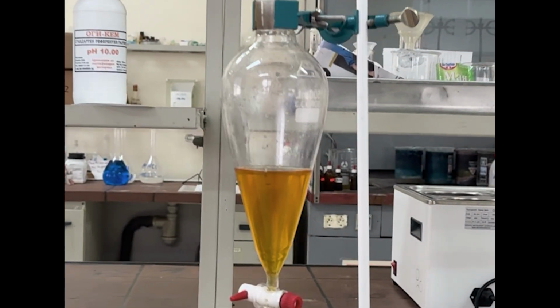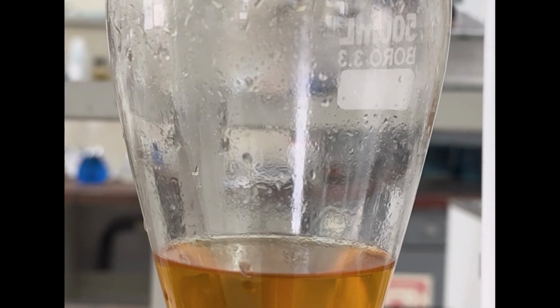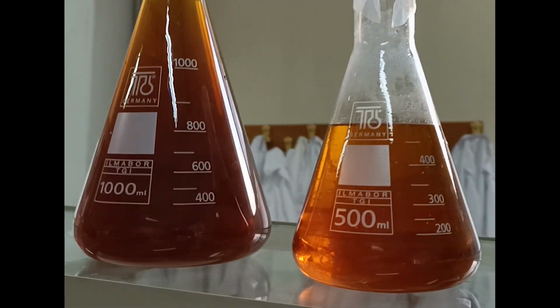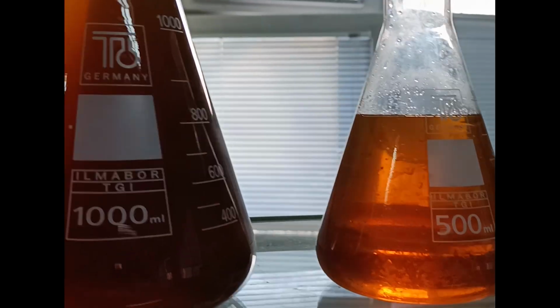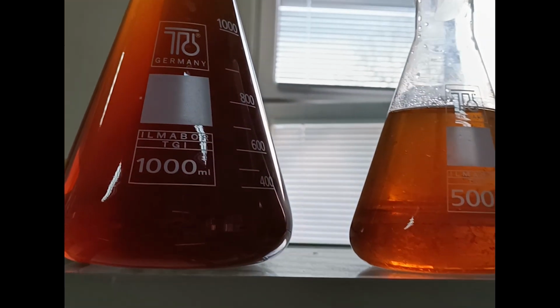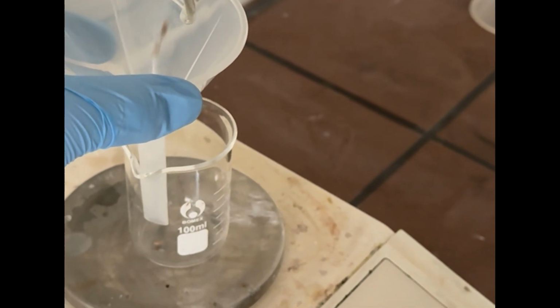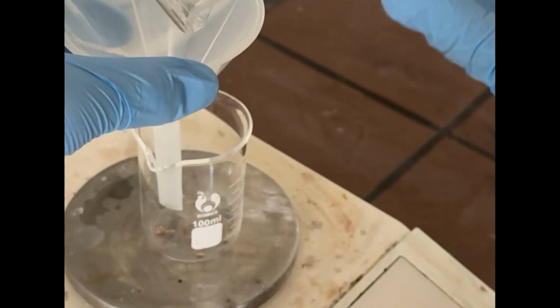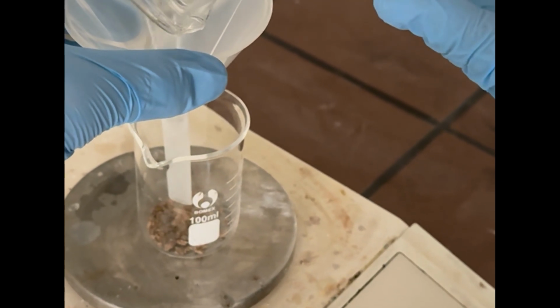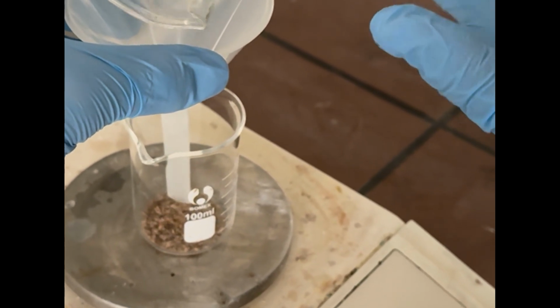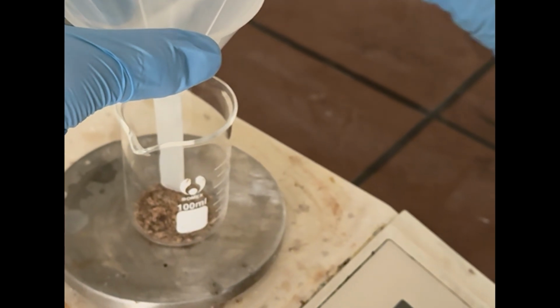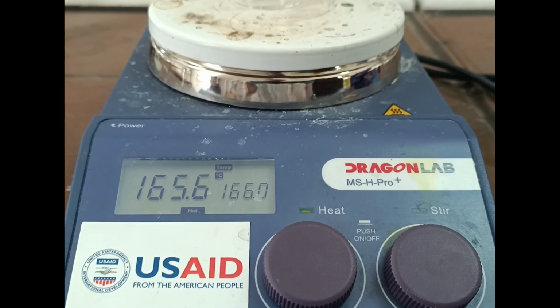Benzimidazole is much more soluble in dichloromethane, or DCM, than in water. So repeated DCM extractions transfer nearly all of the product into the organic phase, while inorganic salts and polar byproducts stay behind. After evaporating the solvent, we obtain some pale crystals, which in our case had a bit of brown, which turned out not to be a problem. Purity is especially important here, because leftover OPD strongly coordinates zinc ions and can disrupt the ZIF-62 crystallization.